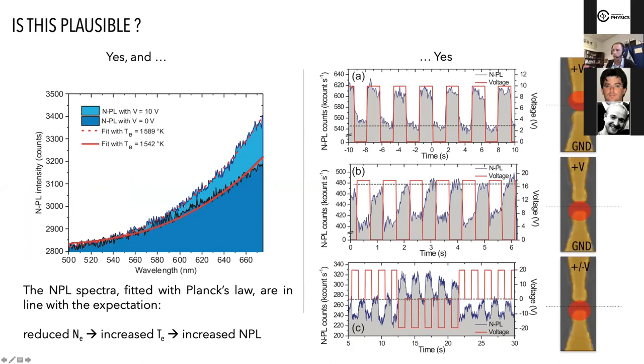So we took the very easy experiments. We took spectra at the positive bias, this one, and spectra with zero bias, this one. We fit that with Planck's law, and we find two different electron temperatures, which is consistent with what we found. Basically, if we have a reduced number of electrons, we have an increased electron temperature, and therefore we expect an increased nonlinear photoluminescence. And we put this also to the test in the following experiments.